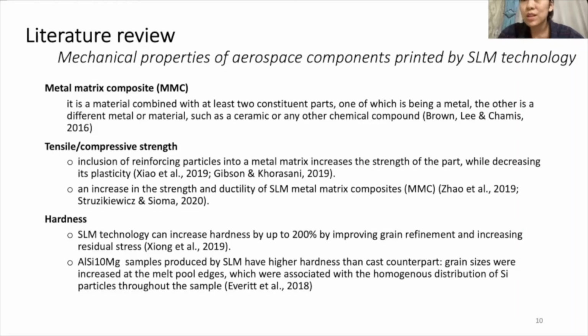There are many previous studies comparing the strength and plasticity of aluminum and titanium matrices with components produced by conventional methods. According to results, the strength of selective laser melting printed titanium and aluminum parts was significantly higher than their monolithic counterparts. Furthermore, the results have shown that the inclusion of reinforcing particles into a metal matrix increases the strength of the parts while decreasing its plasticity. However, recent studies have shown an increase in the strength and ductility of selective laser melting metal matrix composites.